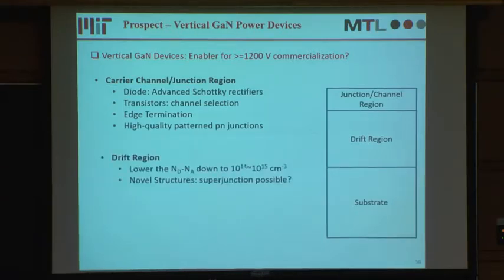For the drift region, it's very important for material scientists to lower the net donor concentration in the gallium nitride drift region down to the 10 to the 14 to 10 to the 15 level. This is the key to demonstrating several thousand volt applications. It's also possible to demonstrate some novel structures for this drift region, such as superjunction.